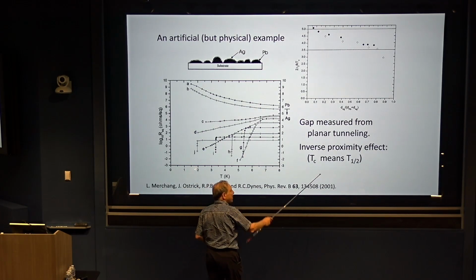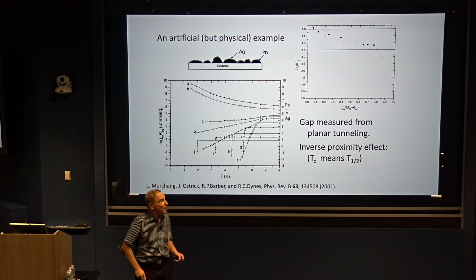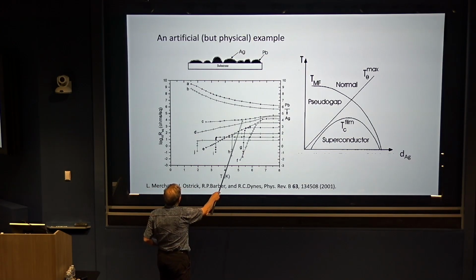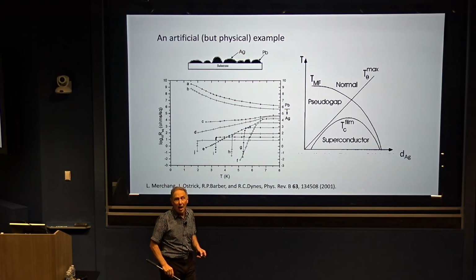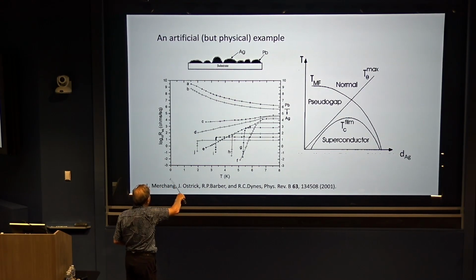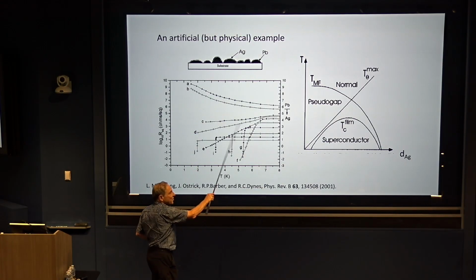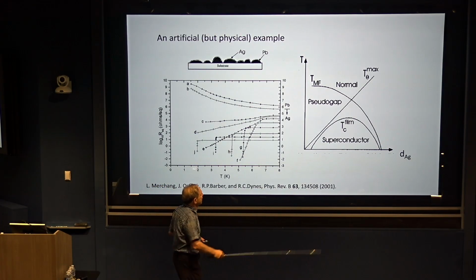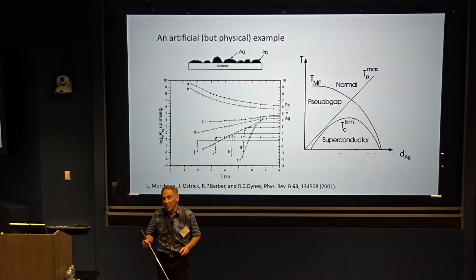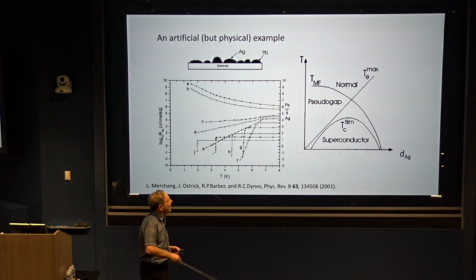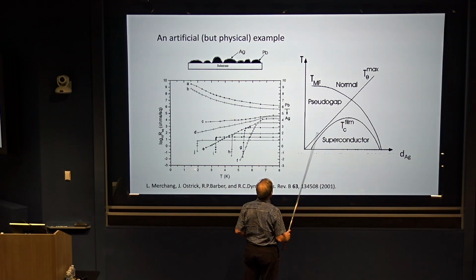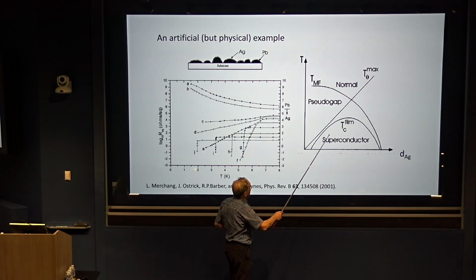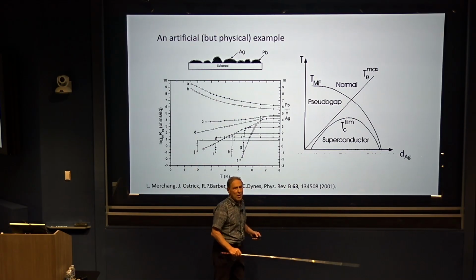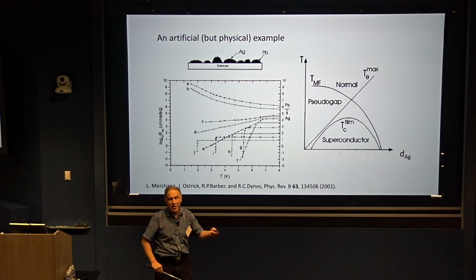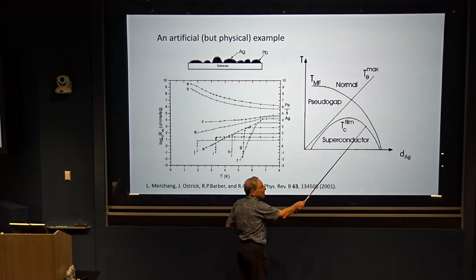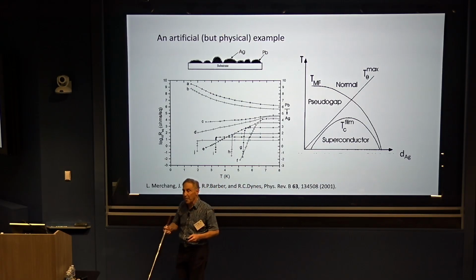That's the inverse proximity effect. The gap is getting smaller and smaller as you put on the silver. But on the other hand, what you can see is long before that, you're getting a lot of superconductivity. This is, I should stress, a log plot, so this is many orders of magnitude drops of resistivity. And so they drew this phase diagram, which of course looks alarmingly like the phase diagram I drew at the beginning, except here it's silver coverage on this axis. And again, you see a crossover from where the silver produces more Josephson coupling, so helps with phase stiffness, to a region where silver hurts by the inverse proximity effect.